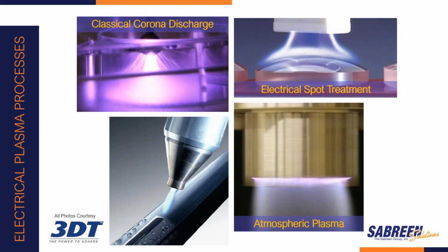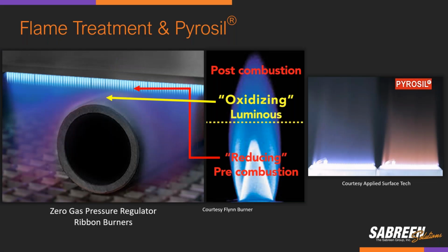With atmospheric plasma, that utilizes a narrow nozzle or circulating rotating electrode powered by an electrical generator and step-up transformer and air, this pretreatment process can clean dirt, debris, and hydrocarbons from the substrate and is excellent for that purpose. Additionally, it can create fine etching for mechanical bonding. Ozone formation is negligible. And remember, there's no such thing as zero potential or potential free that a salesperson may tell you. It should be referred to as near zero potential.